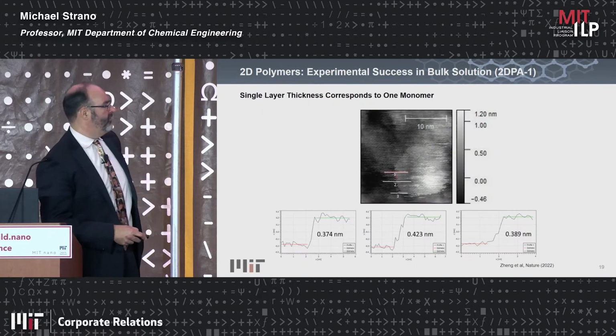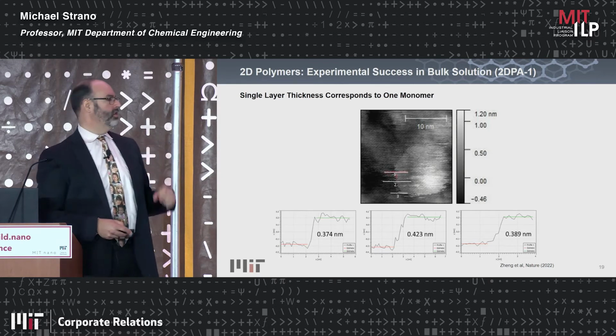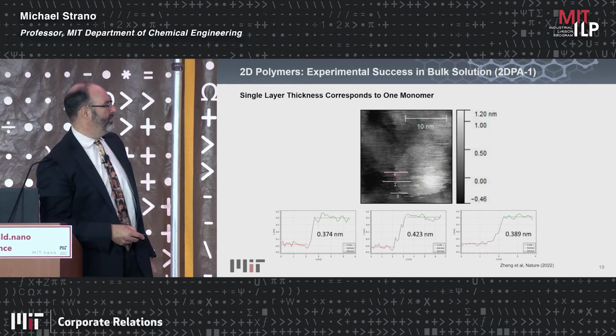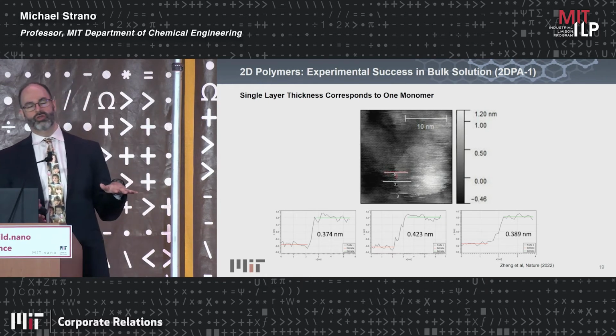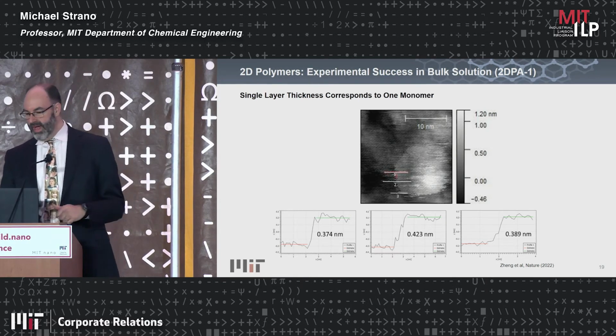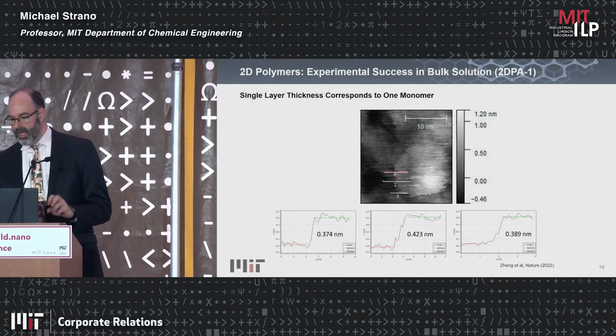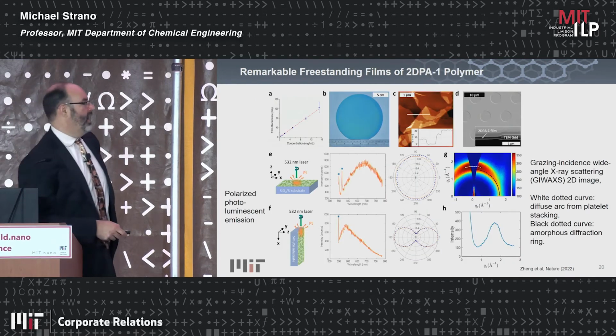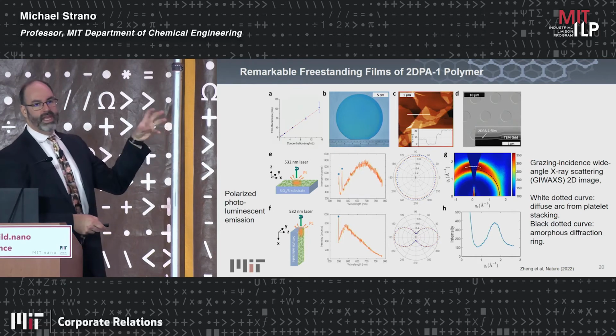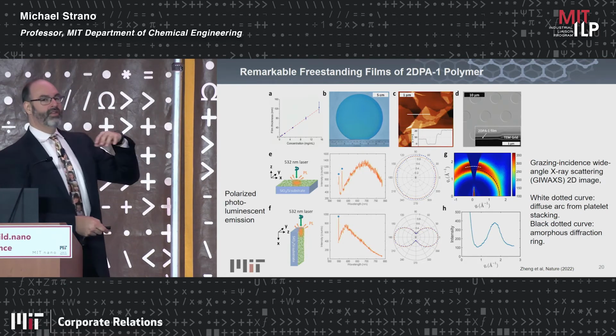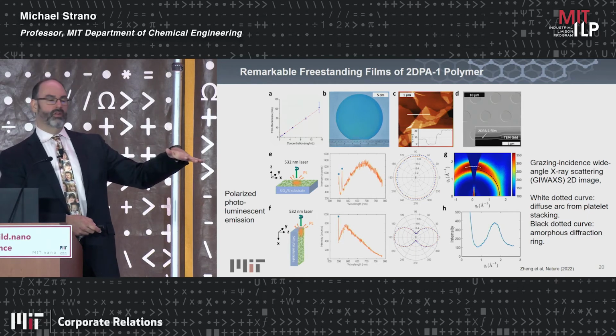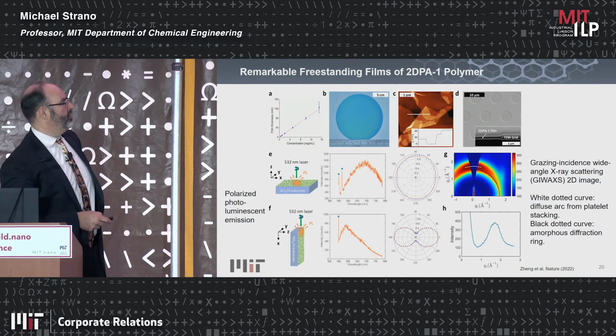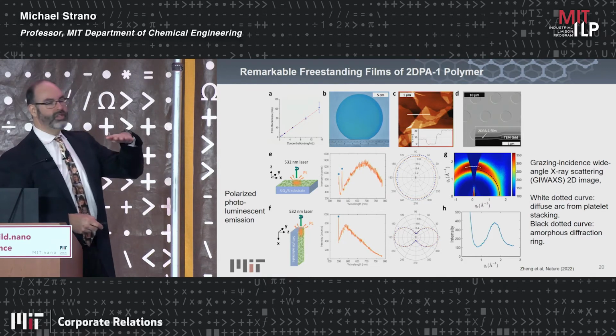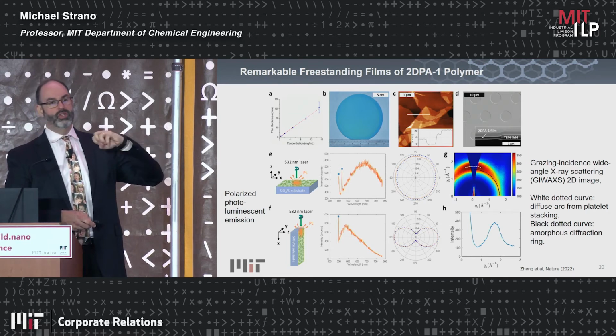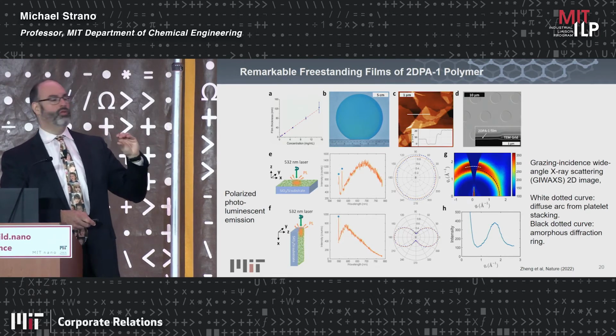The gold standard in the field is to show basically a single atomic layer thickness, which you can see here. This is by AFM. If you spread this on a surface, you get little molecules that are atomic level thickness. This is a technical talk, but I'll just go through some of this. If you take the material, you redisperse it in a solvent. The very first time we tried to spin coat it as a film, we made a beautiful film, and you can control the thickness. And you can see that the surface itself has these steps. So these platelet-like molecules organize. They just spontaneously self-organize and align, and it's through that hydrogen bonding.